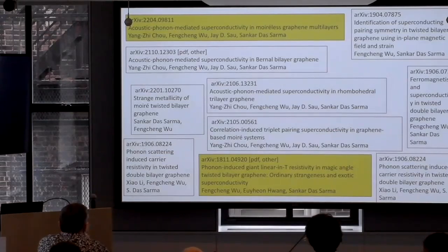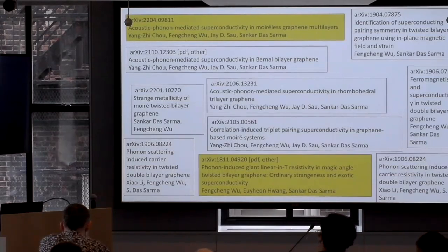We are doing the full resistivity calculation in all these systems with the full band structure. It's kind of like the DMFT calculations you guys do, but for electron-phonon interaction. A complete calculation. My real goal is to see whether we can push the low-T linear resistivity coming from phonons all the way down to like 50 millikelvin. It goes down, but I don't think it goes down to 50 millikelvin. And this paper apparently is almost ready, and we should be posting it soon.